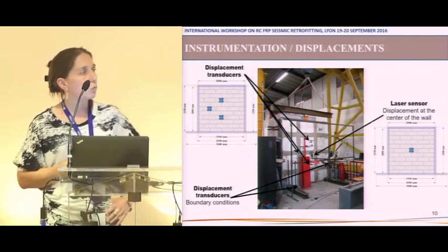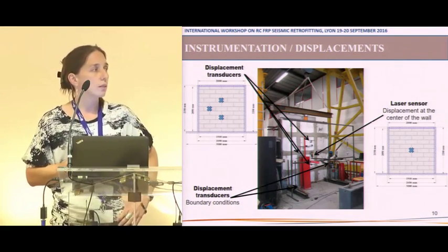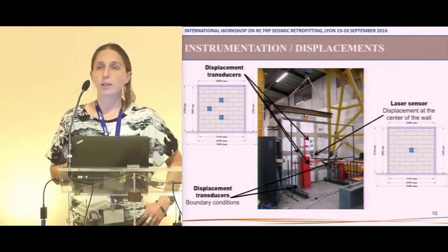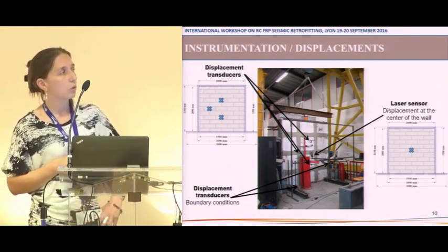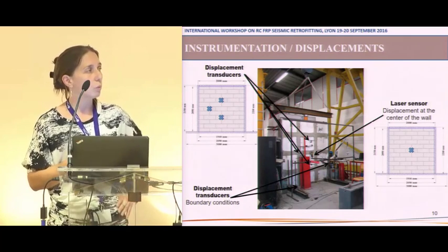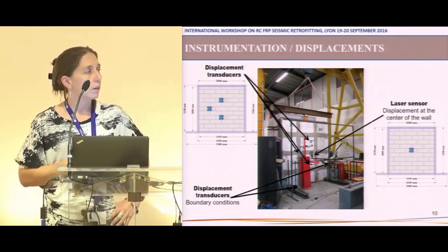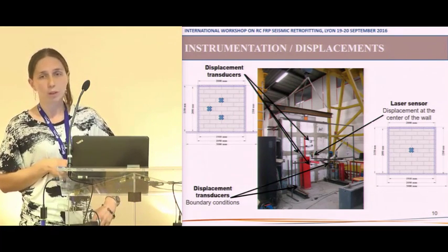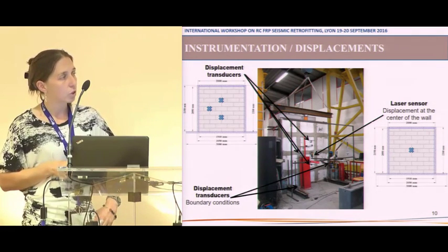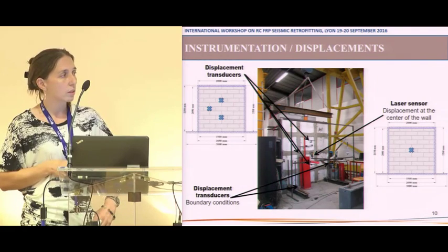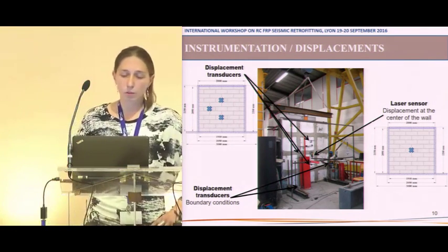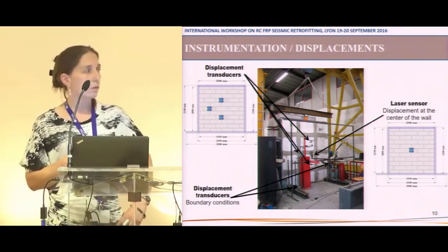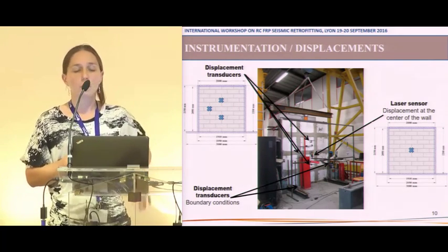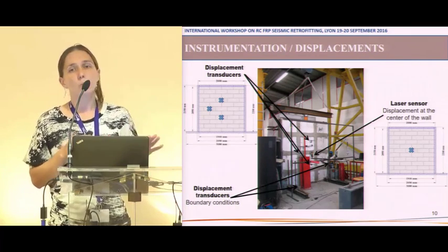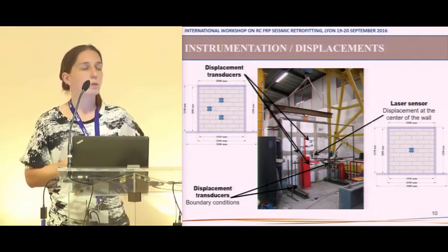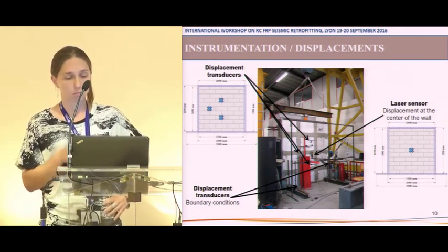To monitor the response of the walls, we have 1 laser sensor and 5 displacement transducers. The laser sensor provides information on the displacement at the center of the wall, and 3 other displacement transducers give the displacements of 3 points over the surface. Then the additional 2 displacement transducers give information about boundary conditions. One is located on the channel section at the base, and the other one is located on the vertical channel section. It appeared that in our test there is no slip, so the test setup prevents the wall from slipping, but we have little displacements on the vertical channel section. So to compare the walls between them, I have decided to work with the relative displacements between the center of the wall and the lateral channel section.